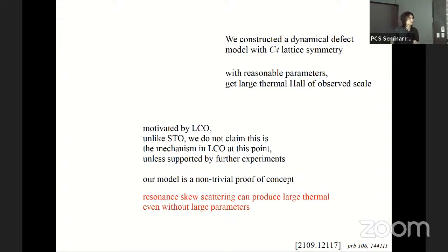Also, the value of this kappa that you are calculating, are they comparable? With reasonable parameters, we can generate a value comparable to the experimental observation. I meant in LCO and STO. Yes, they are of the same order of magnitude, a little bit larger in STO, but the same order.